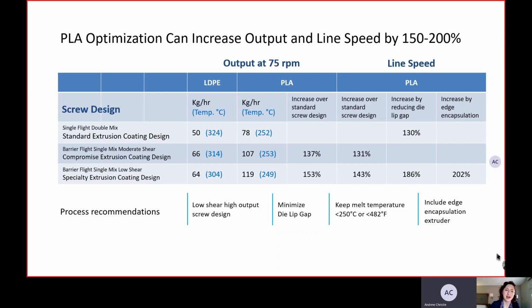Okay, if you have the compromise screw, that had lower shear and it increased the output of PLA because we can maintain that acceptable melt temperature at 253. We can get 107 kilograms per hour, which is an increase of 137% of throughput, and the line speed, 130% again. Now you can see the impact of combining these things.